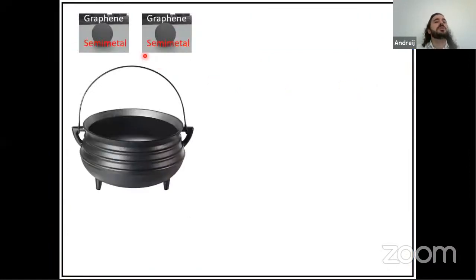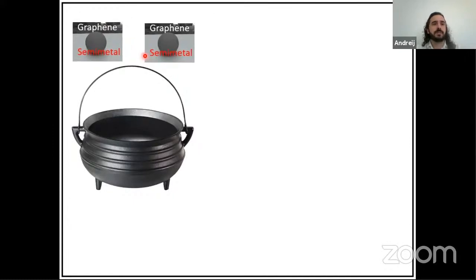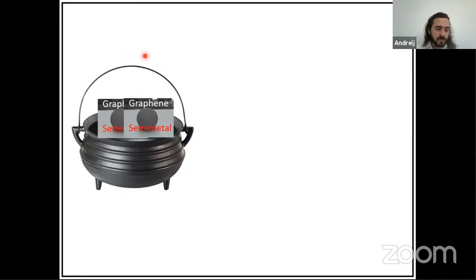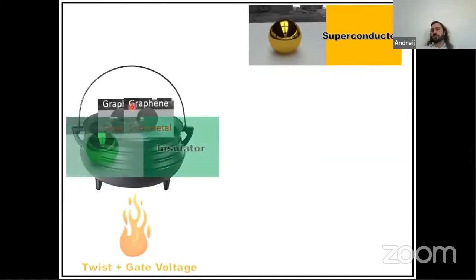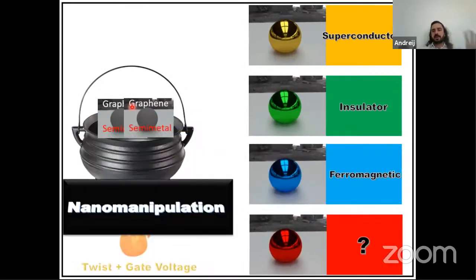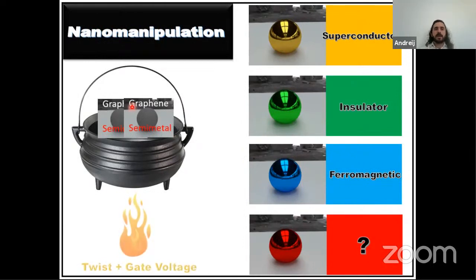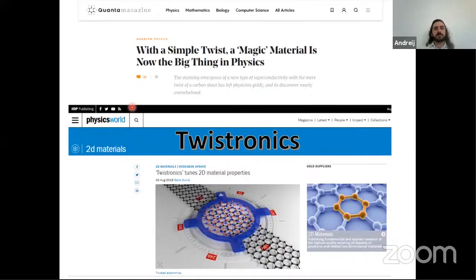But the main point here is to show that by merging two graphenes, which are semi-metals, in a nano cauldron, by warming it with twist and gate voltage, we made two semi-metals become a superconductor, an insulator, a ferromagnet, and this new material that I will show later. So the TBG is a very special system where nanomanipulation is applied in a really beautiful way. Okay, so some other researchers used the same engineering to twist other layered materials, and so a new area emerged, which is twistronics. It is very fresh and new.